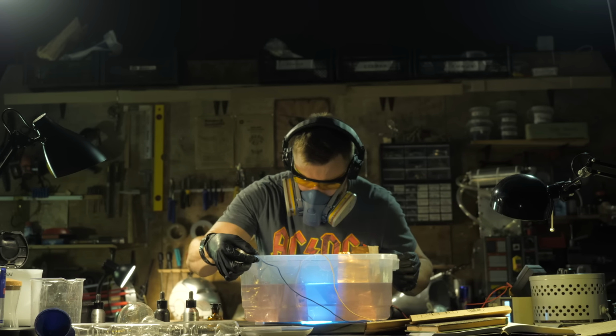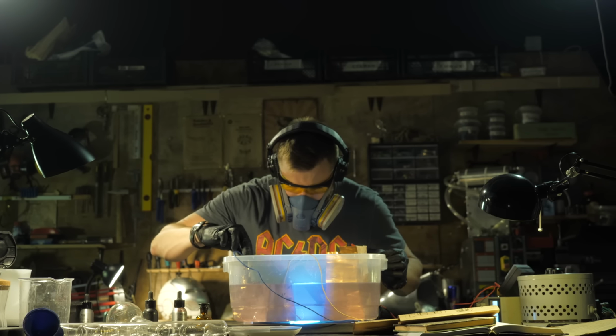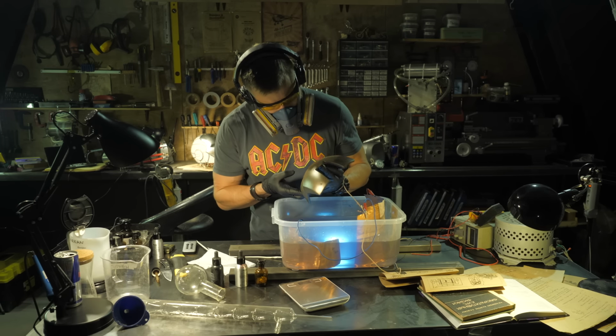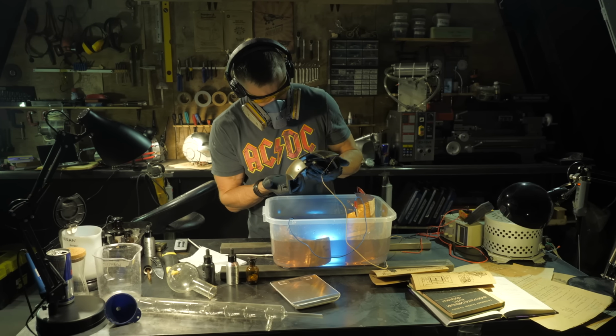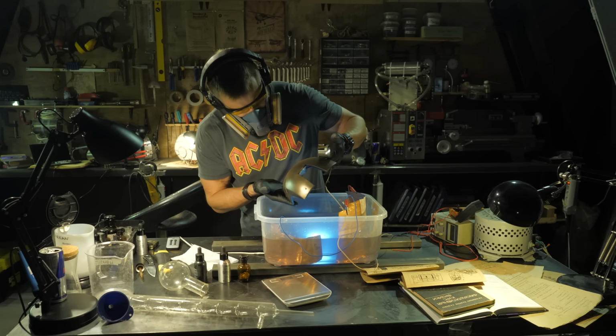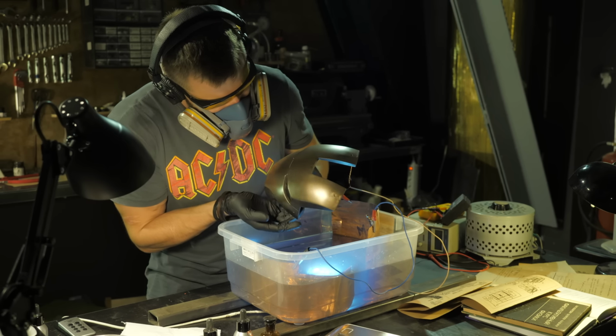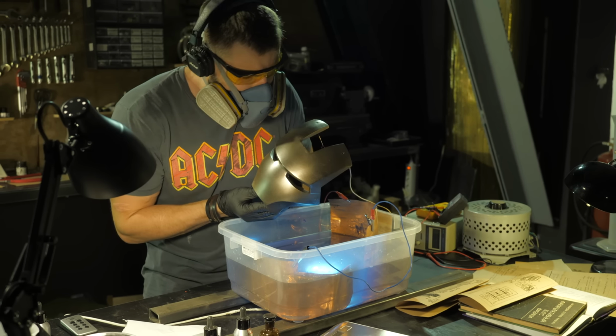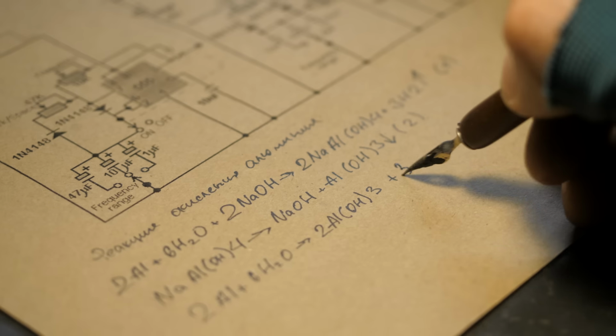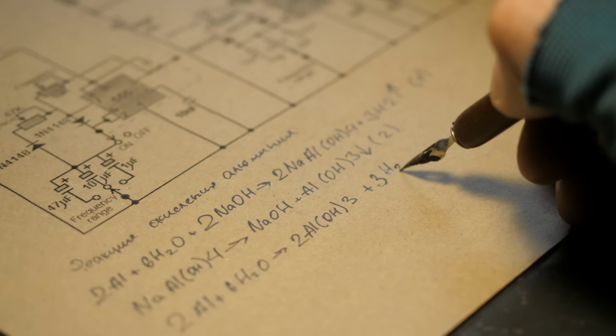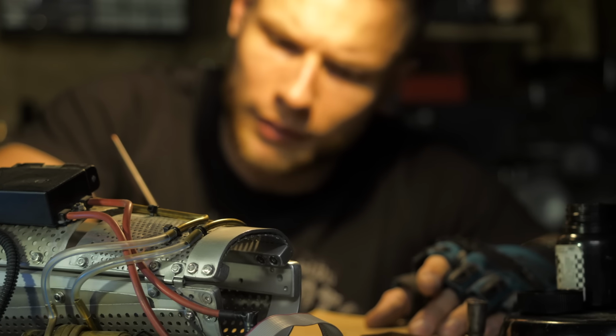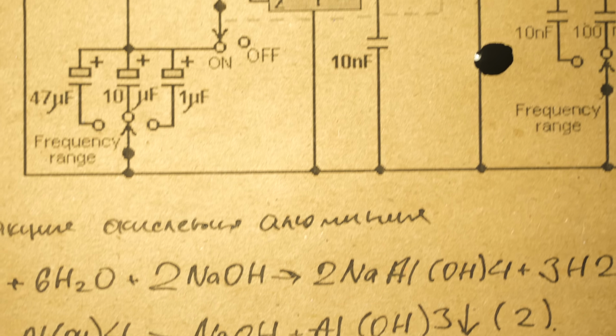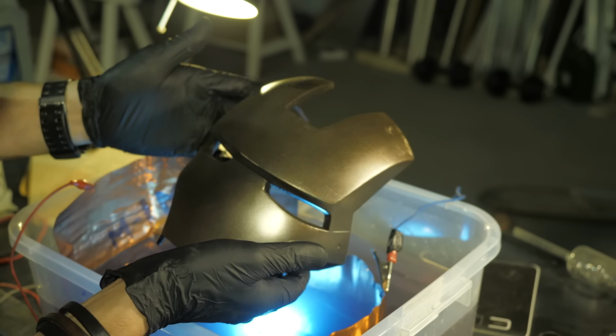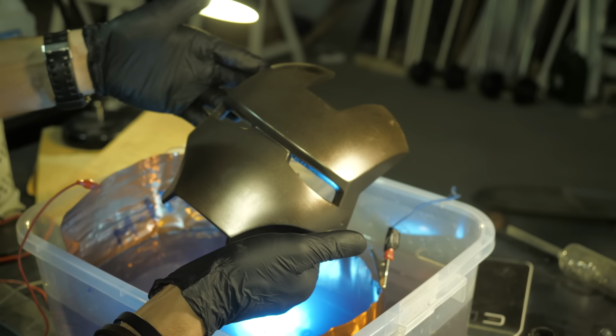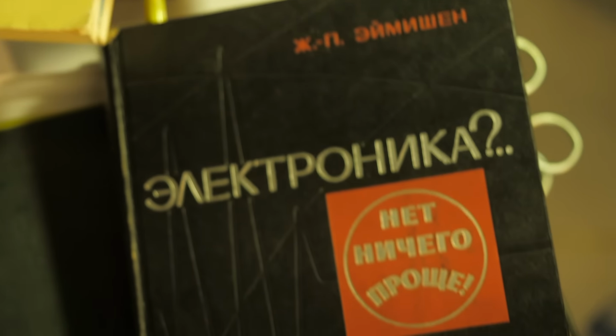I spoiled the first few samples because the coating was uneven and loose. But with persistence, one old Soviet book from the 80s, and with all the power of Soviet engineering, I was finally able to achieve a relatively even copper plating. It turns out that electrolysis with direct current and pulse current electrolysis give completely different coating quality. Deposition with a pulse current with a certain duty cycle and current density gives a metal crystal structure of a completely different quality.